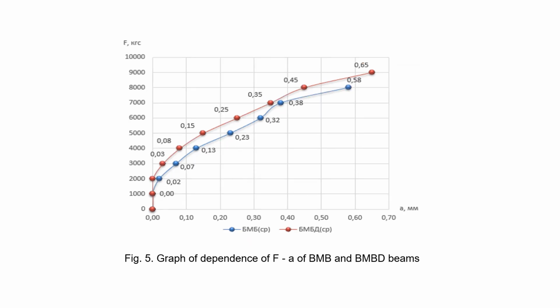The development of normal cracks in beams with hybrid, metal, and basalt-plastic reinforcement of the BMB and BMBD series can be divided into two stages, before and after the onset of metal reinforcement yielding. At a level of 0.2 to 0.3 of the destructive load, the first normal cracks began to appear. Up to a level of 0.4 of the destructive load, the performance of the beams was similar to the BM and BMD series beams, which is explained by the predominant influence of metal reinforcement. After the appearance of reinforcement yielding, basalt-plastic reinforcement begins to exert the main resistance to load. The behavior of the beams becomes similar to that of the BB and BBD series.